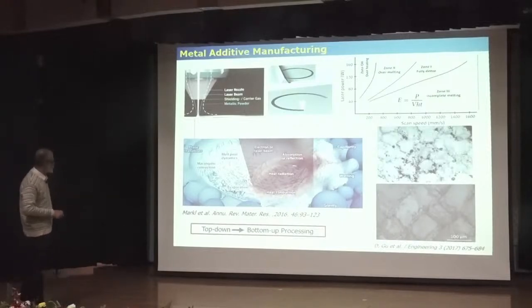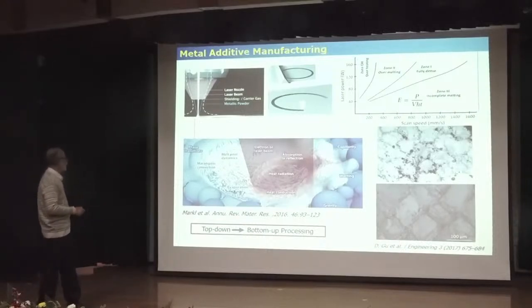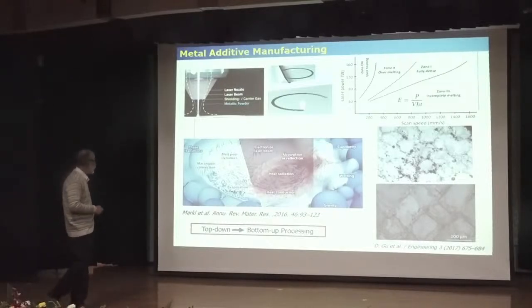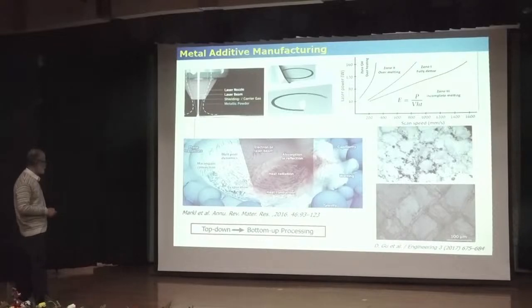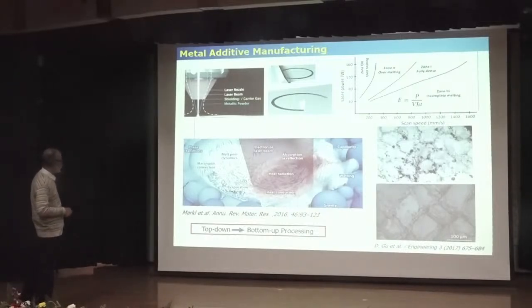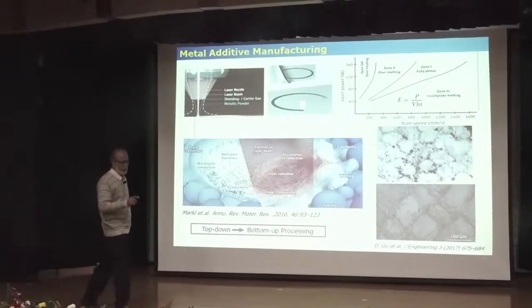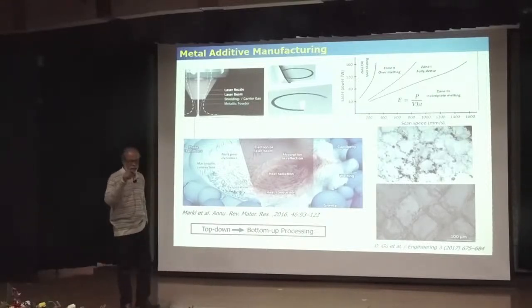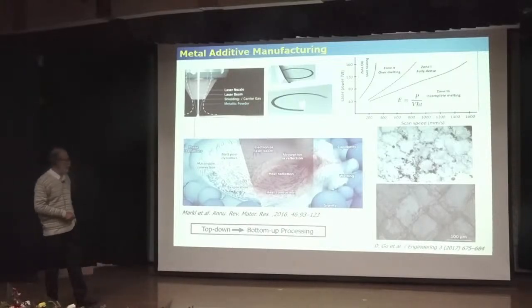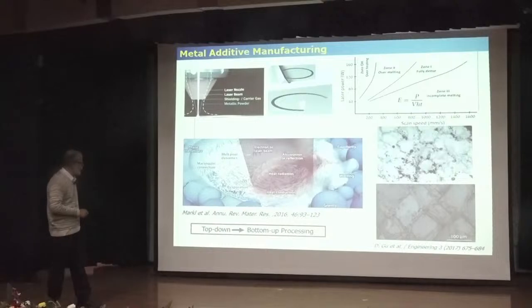Phenomenologically, under the laser beam, there are thermal radiation, thermal conduction, absorption and reflection of energy, and there is also turbulence. And there are different complex mechanisms which take place here, because this is basically a capillary effect. There is no large scale solidification behavior of a metal pool. So it is melt pool dynamics, evaporation, Marangoni effect. In other cases, surface tension is a function of temperature, but here surface tension depends on temperature gradient, wetting. So there are several complex phenomena.